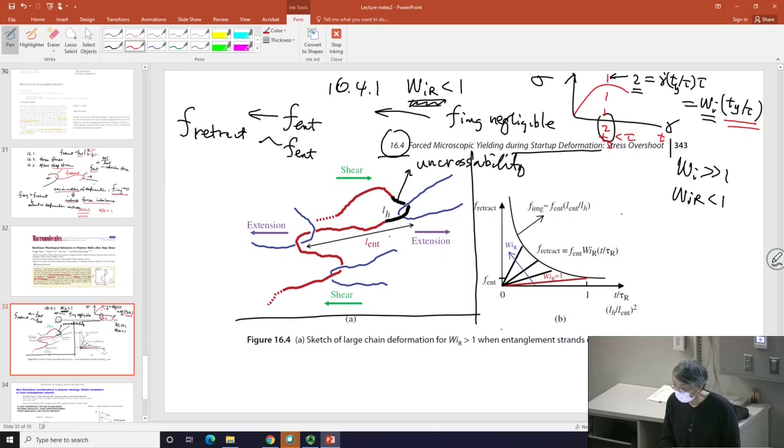Let's focus on a case where it was interesting, I think we just call it 16.4.1. It was interesting to find out whether we can understand, in this so-called elastic deformation regime, this yield strength, which is known experimentally to go with the shear rate as 1/3 power.